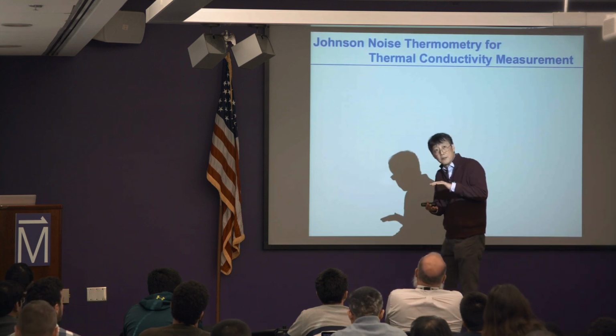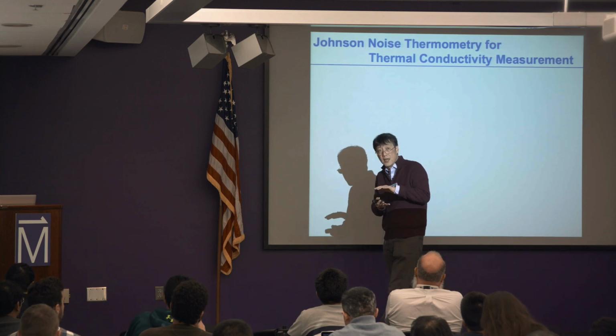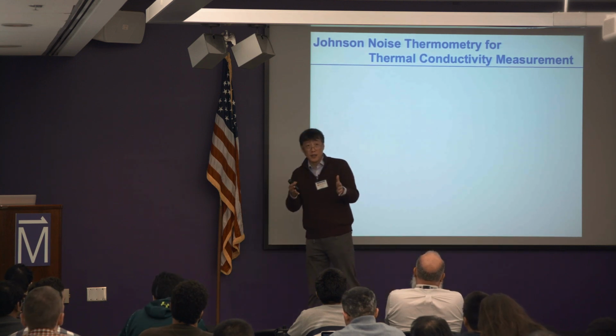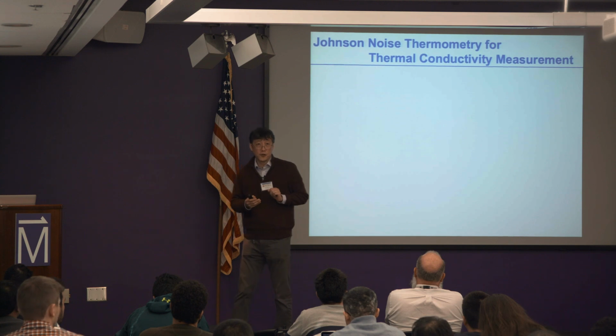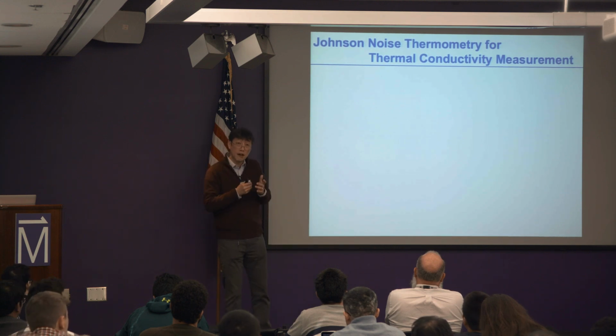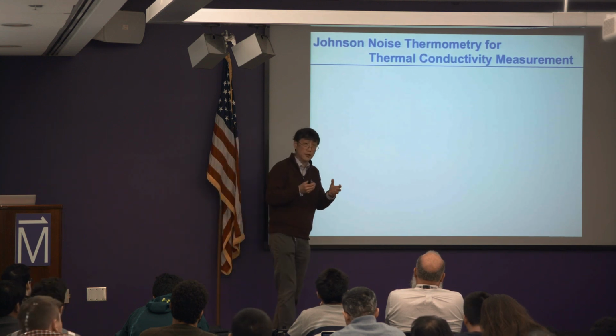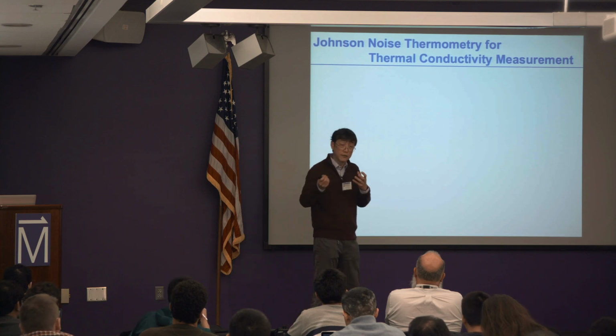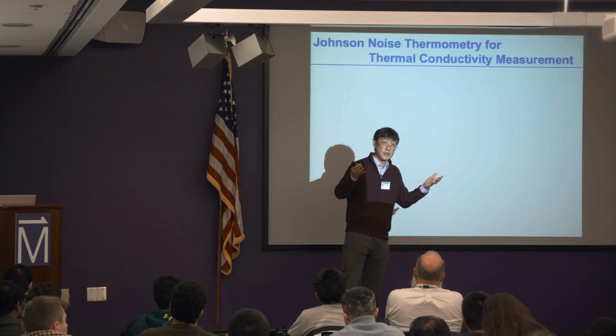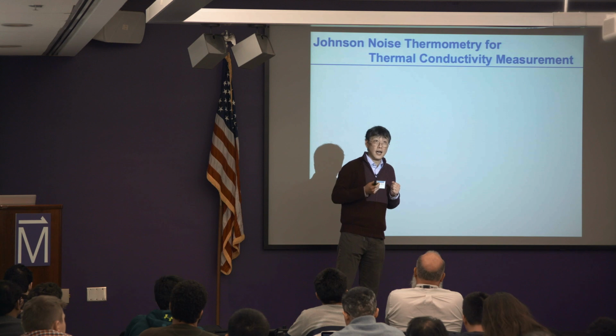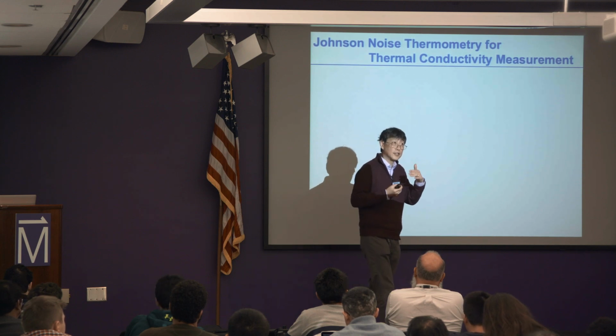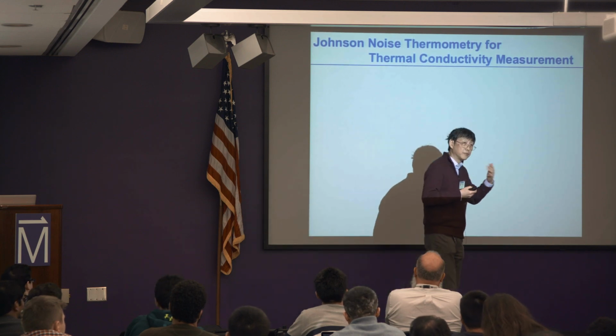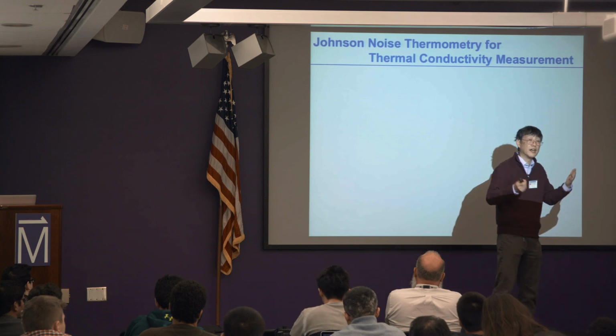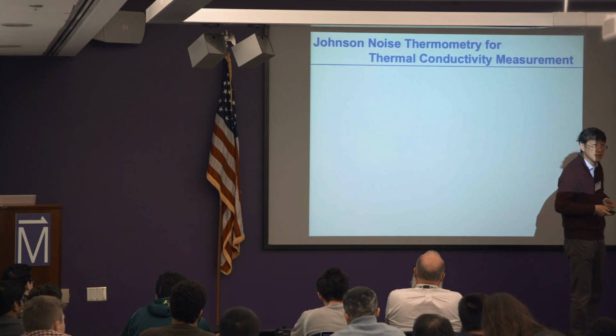So I want to decouple the electron and the phonon system by just making the sample size small enough, small compared to the electron-phonon length scale. And this can be achieved in graphene rather easily, because the electron-phonon coupling, especially electron to optical phonon coupling, has a reasonable length scale at finite temperature. Therefore, I can stay within these arguments up to reasonably high temperatures, something like 100 kelvin or even 200 kelvin in some cases, right?